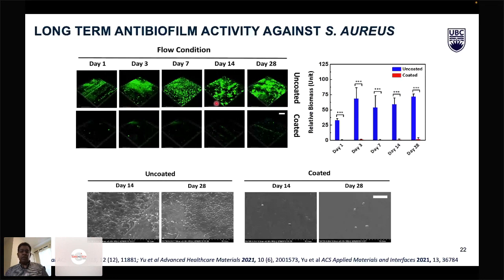You can see the cursor. This is the control substrate. And on this substrate, after 28 days of continuous exposure to the bacteria culture, you don't see biofilm, or see very minimal biofilm formation or bacterial adhesion. And we calculated the biofilm, which is SYTO green labeled bacteria there. On the right side, you can see the biomass deposited, and you can see almost a 98 to 99% decrease in the biofilm deposition over 28 days.